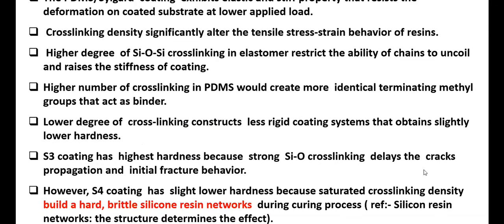Strong Si-O cross-linking delays crack propagation and initial fracture behavior. The S4 coating has a slightly lower hardness because of saturated cross-linking density, which builds a hard and brittle self-linking silicon resin network during the curing process, and the silicon resin network structure determines the effect. Okay, and this is why when the cross-linking becomes higher, the hardness becomes lower. That means it becomes more brittle. It builds a hard and brittle silicon resin network during the curing process, and it fails and becomes a brittle coating.